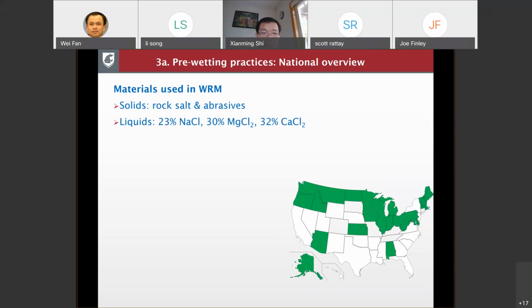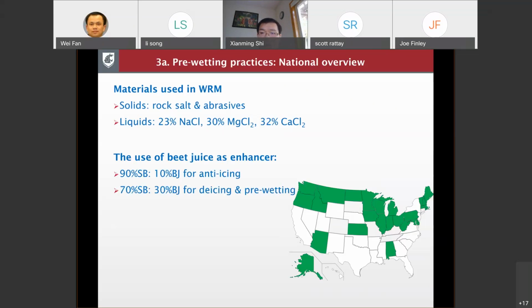Mostly people are still using rock salt and abrasives as solids, and then using sodium chloride, magnesium chloride, and calcium chloride as liquids. And there's a little bit newer trend, which is that the use of beet juice is becoming more popular as an enhancer. The typical blend for anti-icing is you blend beet juice with 23% sodium chloride brine at a 10 to 90 volume ratio. And for de-icing and pre-wetting, the beet juice dosage is higher, typically 30%.